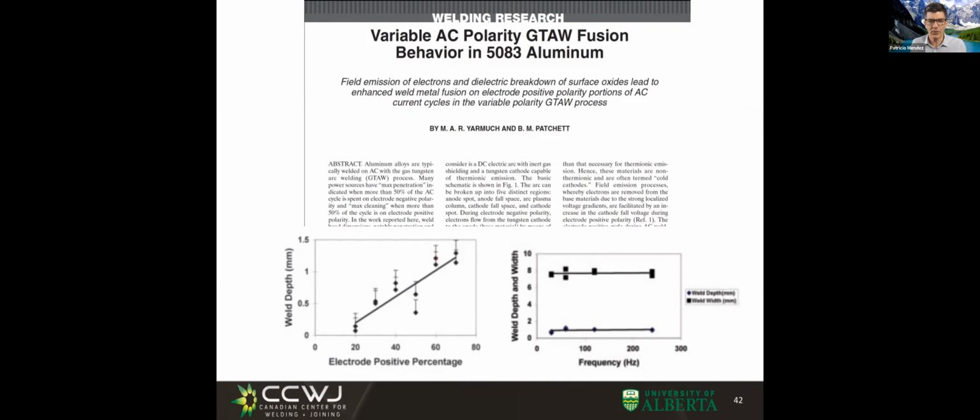And does frequency matter? No, unless you get into the transient of the arc, frequency doesn't really matter, because as long as your machine responds fast enough, all you're doing is having the same combination of the same two things, just like whether you hash it finer or coarser. Very, very interesting. These friends wrote a whole paper and did a lot of experiments for something that you could anticipate from the formulas in the class. Powerful and modern.